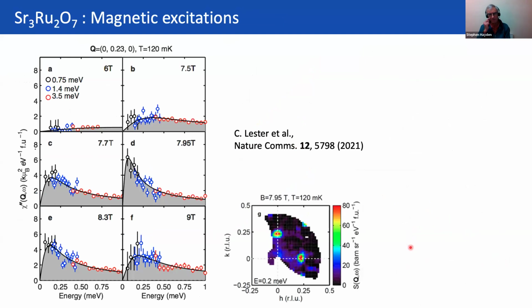So anyway, just on strontium ruthenate, the connection with the spin fluctuations. Here we've got the measured spin fluctuations in strontium ruthenate measured on LET, and you can see here two points in reciprocal space where there are strong low energy spin fluctuations. The energy scale of these spin fluctuations varies as you change the field. And you can see here at low fields, they're kind of out of the window of the experiment, which goes up to about 1 meV here. And as we go through the quantum critical point into higher fields, we get these very low energy spin fluctuations, the gray regions here.